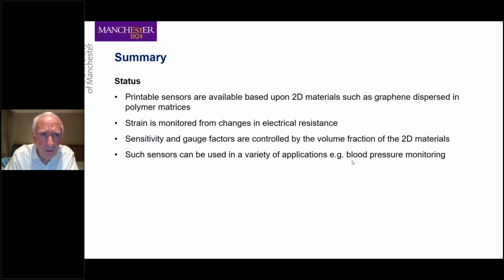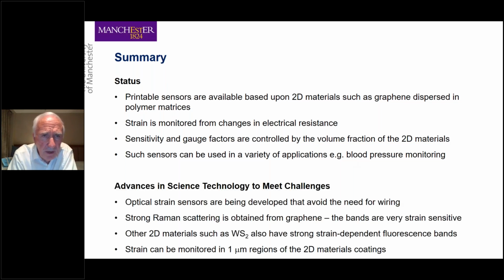That's the current status, but looking into the future, I think here we have a completely different way of doing things, by using optical strain sensors, where we don't need any wiring. We just have to shine a laser beam. We could either do it from graphene with Raman scattering, or we can do it with other 2D materials such as molybdenum disulfide, tungsten disulfide, and tune into the strong strain-sensitive fluorescence bands. And there are various advantages of this technique. Particularly, we could measure strain in 1 micron regions, or if we defocus the laser, of course, we could take a more average strain. But that gives us quite a degree of precision in our measurements and a completely new way of doing things.